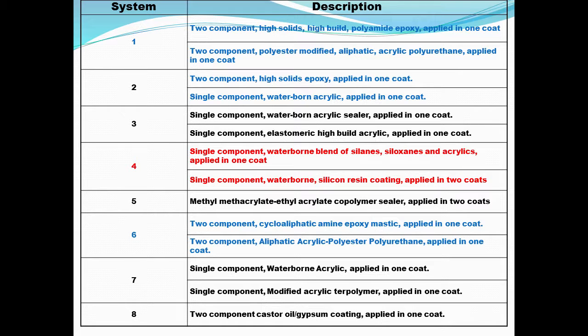Now, some of these others probably went overnight simply due to the cure conditions and when they were applied in the day, but they didn't necessarily require a 24-hour cure. And then these 3 coating systems that are blue, and I am from Kentucky, so everything good is blue, so I colored them blue. Just remember as we go on through this, these 3 systems are all 2-coat systems with an epoxy primer and then either a urethane or an acrylic topcoat. Generally speaking, under good conditions, that second coat can be applied in the same day.